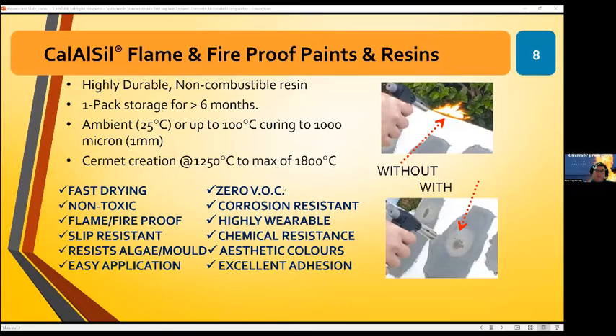It's very important. Zero volatile organic component. That's particularly the non-combustible resin. The hybrid resins have a slight bit of solvent from the organic polymers. Corrosion resistant. Obviously, the hybrid polymers are far more corrosion resistant because I do get liquid seal, and if I get the 150% binder quotient, so I get 3 parts organic binder to 2 parts ceramic binder, I tend to get a product that is in fact air resistant as well, air sealed. So that's quite an accomplishment with a ceramic.